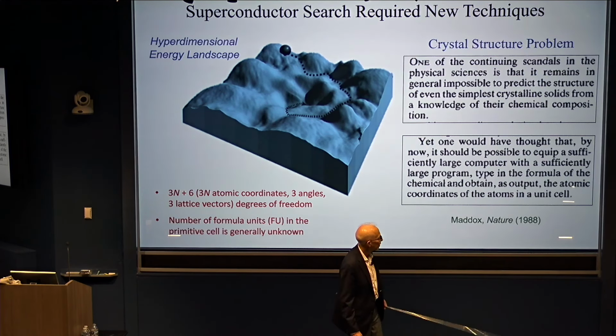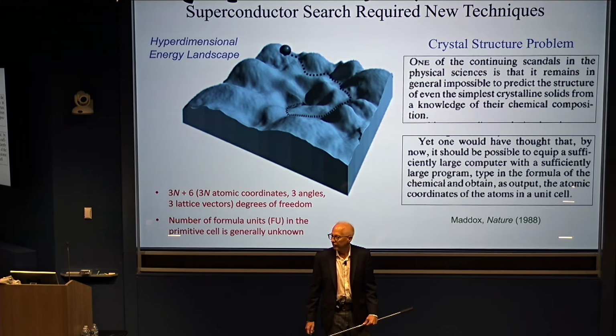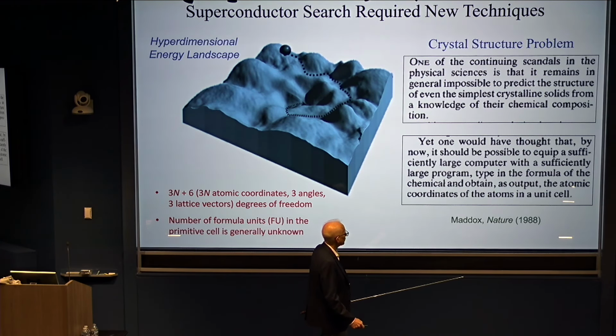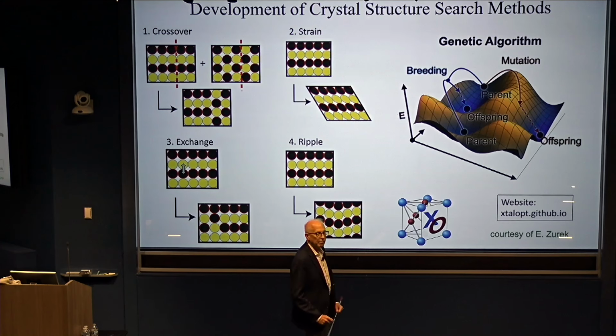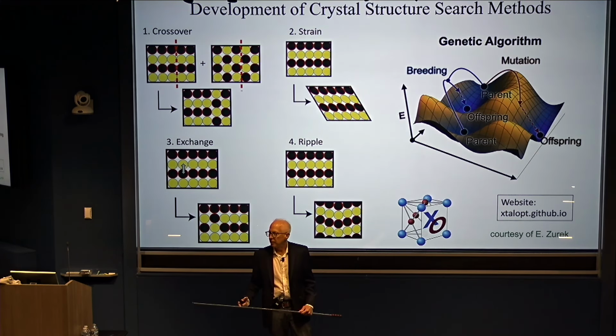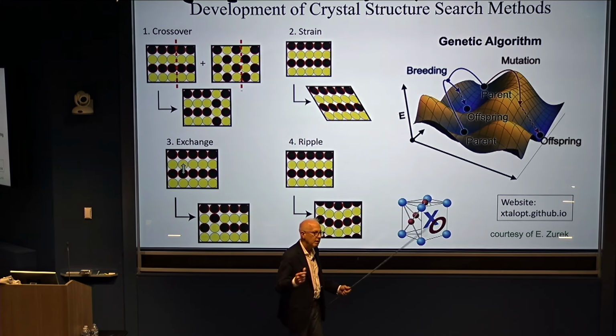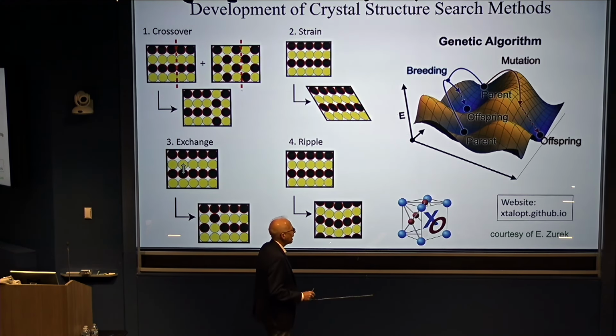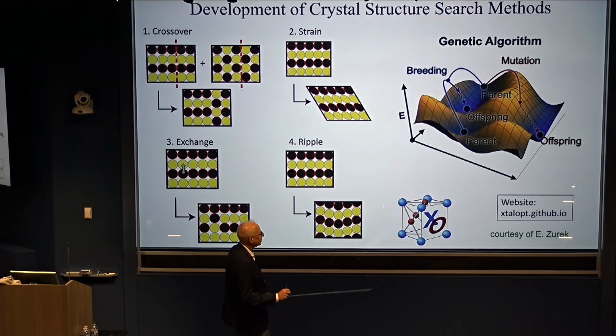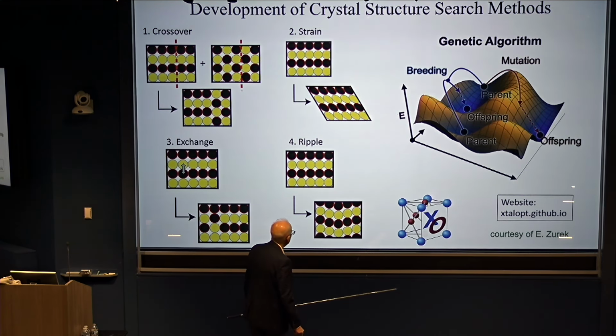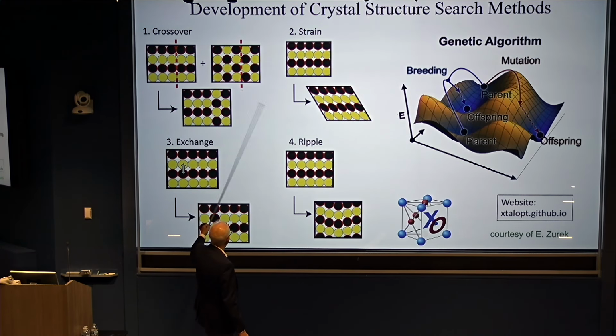So this challenge was met due to the efforts of a large number of groups over the intervening 10 or 15 years. And this was done by marrying various genetic algorithm approaches using, as Maddox said, very large computers and clever algorithms for exploring space to look for crystal structures. And here's an example of just one. This is due to Eva Zurek at Buffalo, the XtalOpt method. So you take these combinations of elements or atoms, and you can then shear them, make them ripple. You look for energy minima.